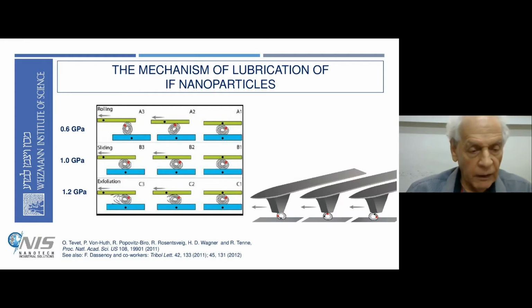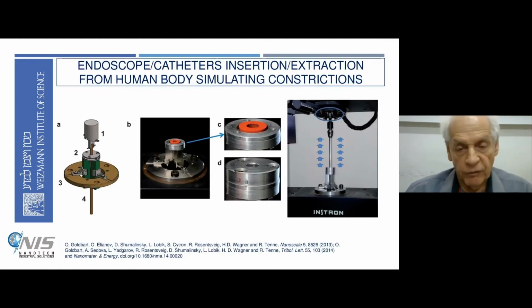Once you apply very large pressure or load, you get exfoliation of the nanoparticles, and these exfoliated nanoparticles lie on the surface and provide extra lubrication until they are consumed, chemically consumed. So this observation was very important to verify the lubrication mechanism and to vindicate that these materials are very good lubricants for a variety of purposes.